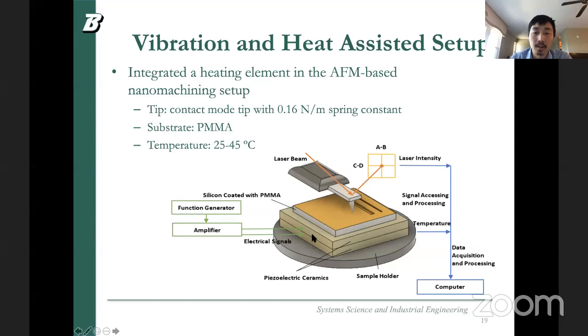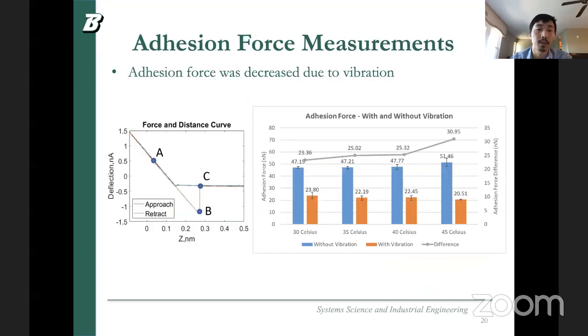We can see the same X and Y vibration. This time we save the Z vibration here, and then we apply the heating element here, so temperature can be applied on the sample. The outside is a commercial AFM. The tip we use this time has a smaller spring constant, quite a bit smaller than in the previous vibration-assisted process. We're going to talk about this later on. The substrate is PMMA, and the temperature, when we do the experiments, is around 25 to 45 degrees C.